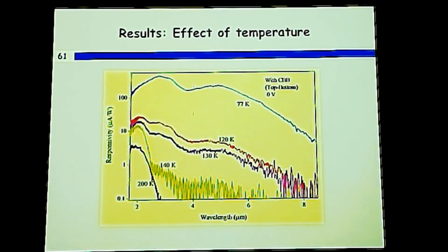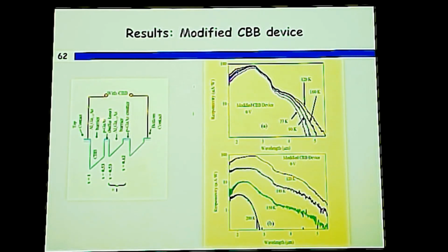So we modified the original device. We removed that thick middle contact to make it narrow, about 20 nanometer, and we also increased the aluminum fraction in the barrier so that the barrier is slightly higher. The reason is we expect the device to operate at higher temperatures.